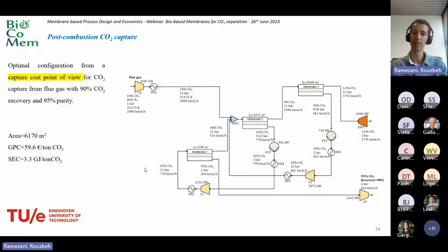Okay, this is the 3-stage optimal configuration for post-combustion to reach 90% CO2 recovery and 95% CO2 purity. The objective is to minimize the cost, not membrane area or energy consumption. So here you can see we reach this separation target with 3 membrane stages at about 59 euro separation cost. The specific energy consumption is about 3.3 gigajoule per ton carbon dioxide, and we need about 6,000 square meter membrane area.